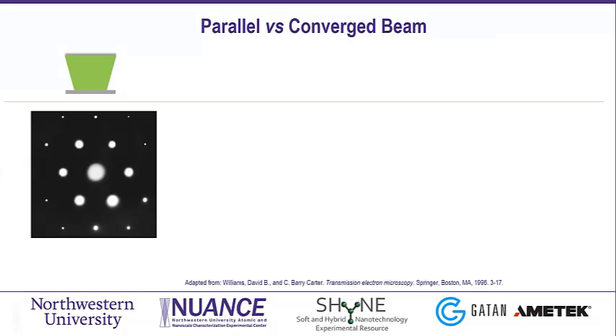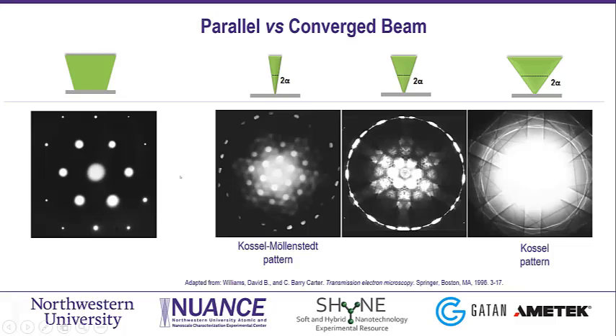Just to summarize a few modes, most of you are probably familiar with parallel diffraction. It's also called selected area diffraction, the SAD for short. So that's the one that you're most familiar with. When you start learning TEM, you start by taking diffraction patterns, checking symmetries of materials, and doing diffraction-based imaging modes, such as bright field and dark field. But there are more that you can do if you actually converge the beam.